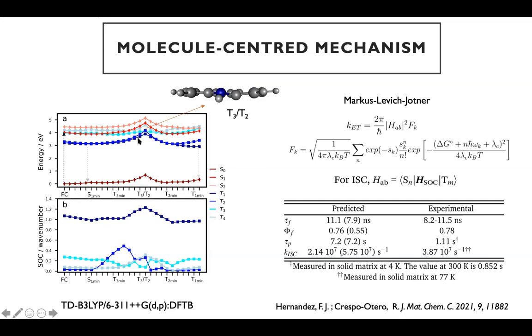And depending on where it relaxes, you may find emission of longer or lower wavelength. And in fact, in the experiments, they find that this kind of molecule shows Kasha emission, that is the regular emission from the first triplet state, or non-Kasha emission. And essentially, if you look at the spin-orbit couplings in these systems, you will find that the values are extremely small, but still the process is facilitated by the high density of excited states that you have here.